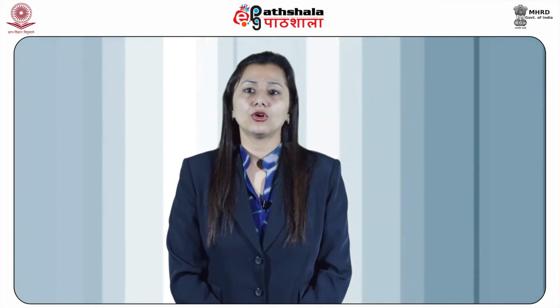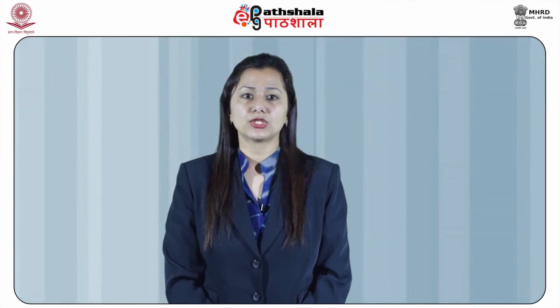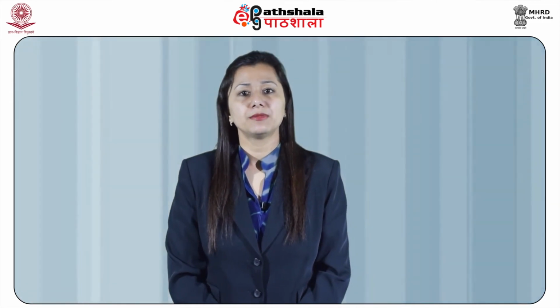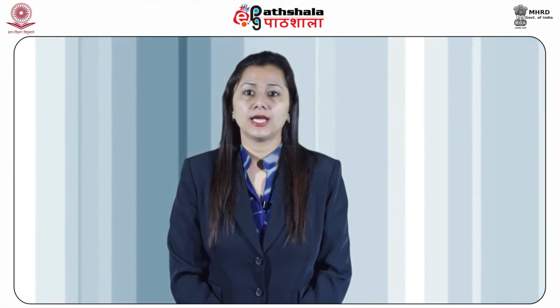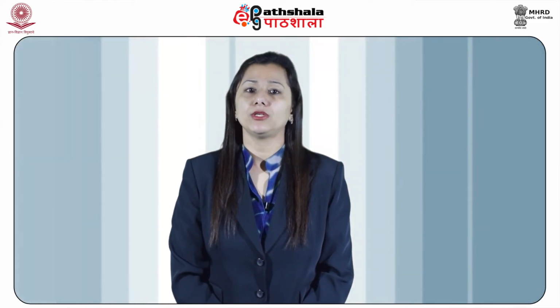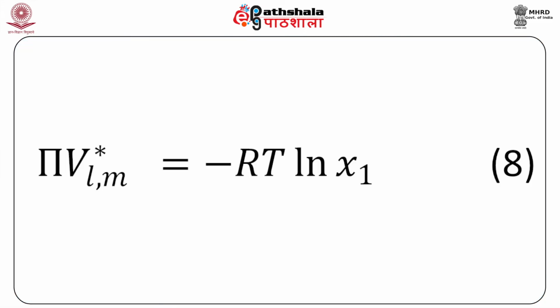The osmotic pressure of a solution depends on its concentration, that is, the larger the concentration, the larger will be the osmotic pressure. The relationship of osmotic pressure with the concentration of the solution can be derived thermodynamically. In this module, we will not consider the entire derivation, but we will only use the following result. Pi into V star Lm equals minus RT ln chi 1, where V star Lm is the molar volume of the solvent, chi 1 is the amount fraction of the solvent in the solution.